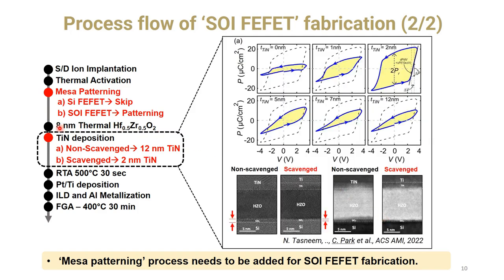And then we deposit 8 nanometer hafnium zirconium oxide, and then we deposit titanium. Here we made different TiN thickness MOSFET devices, and we found that compared with the 12 nanometer device, just a normal reference device, the TiN 2 nanometer device has a higher polarization, 2Pr is much higher compared to 12 nanometer.